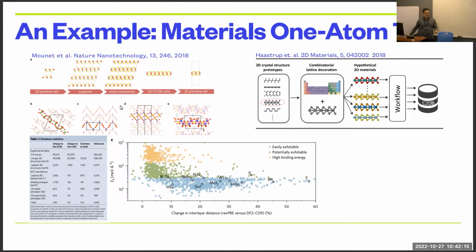And you would think there are billions or trillions of crystal structures that are known to mankind. But as a matter of fact, if you take all the databases of crystal structures, we have about 200,000 unique structures. So we're not speaking about trillions of crystals, right? And so what this group did was very smart: can we look at the topology of these crystals, just looking at the connectivity between the atoms in the crystal cell, and try to figure out if the topology corresponds to systems that are layered? Right? If the atoms are close together in two directions, but farther away in the third direction, then these crystals are really layered systems, right?